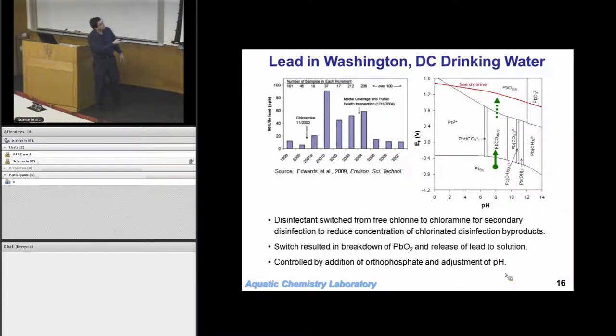That red line tells you where it would be with free chlorine. The blue line shows you where it would be with chloramine. Okay? So with the chloramine, it dropped it from being a solid down into a dissolved compound. This is not good in terms of water quality. You might have solved the disinfection byproduct problem with the chlorine, but you've taken a solid form of lead and started to have it convert over to a dissolved form of lead. So now you see lead concentrations coming out at higher concentrations in people's drinking water.